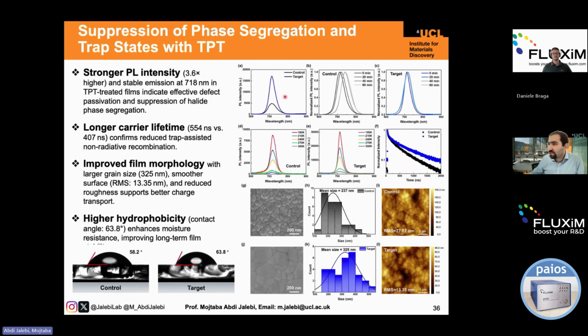So we have observed a stronger PL intensity for what we call target. Target means we are utilizing all the triple passivation in the perovskite devices or thin film structure, and the control means the reference without any passivation. You can see that without the passivation, the PL bandgap is not stable; it's changing over time. With the passivation, there is almost no change in the location of the PL. The PL intensity is significantly higher, and even at different temperatures, you can see that the trend is the same.